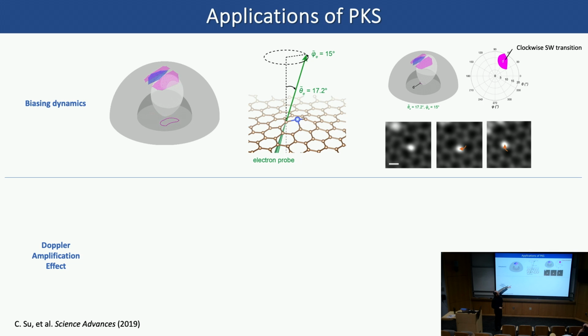No, in this case, we tilt the sample instead. So instead of tilting the beam, we tilt the sample in this way so that it doesn't really affect the electron beam path. So it still goes scattered with the material, still forms all the images as if it's in a normal imaging condition, but your sample is actually tilted in this combination of angles.